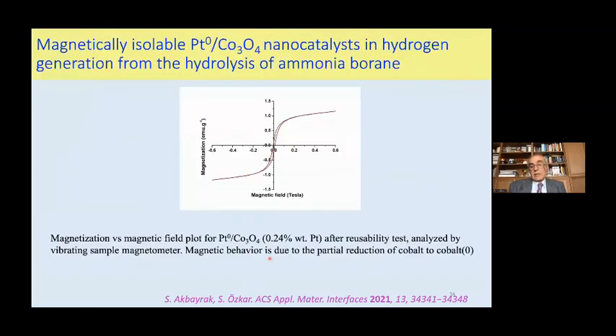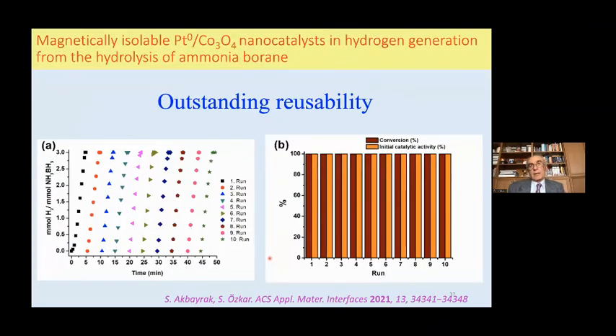So cobalt oxide is magnetic, or became magnetic, and therefore we can use the magnetic separability of the materials to investigate the reusability, which shows very high reusability. After 10 runs, there is no sign of decrease in activity and conversion either. That means even after 10 runs, 100% conversion, that means 3 equivalents of hydrogen per mole of ammonia borane, is obtained with the activity same as initial activity.